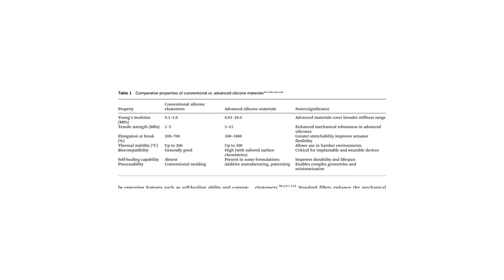To put the advantages of these advanced silicones into perspective, let's compare them to conventional silicone elastomers. Advanced materials offer a much broader range of stiffness, with a Young's modulus from 0.01 up to 10 megapascals, compared to the narrow 0.1 to 1.0 range of conventional ones. Their tensile strength is significantly higher, 5 to 15 megapascals versus 1 to 5 megapascals. Their elongation at break is much greater, up to 1800% versus 700%.